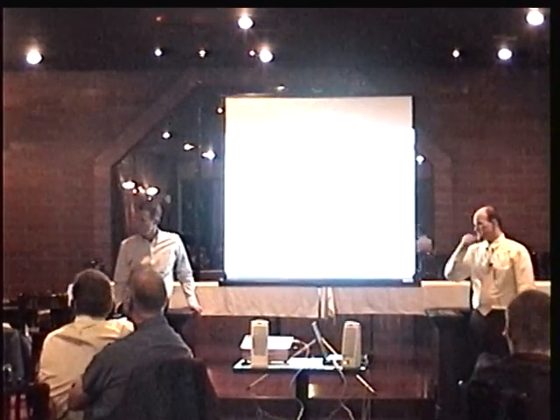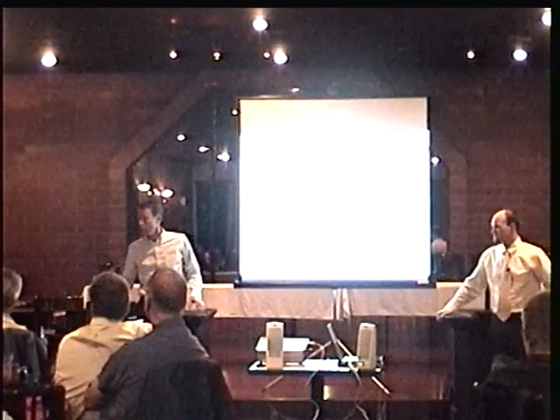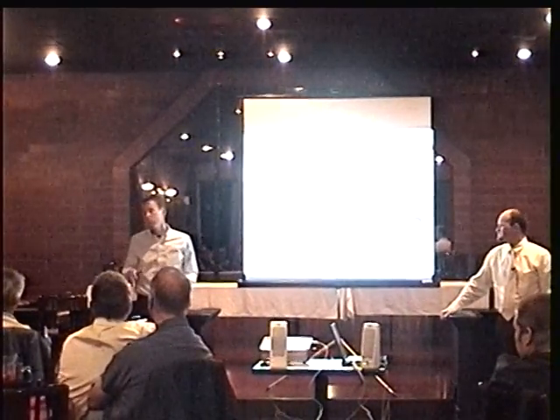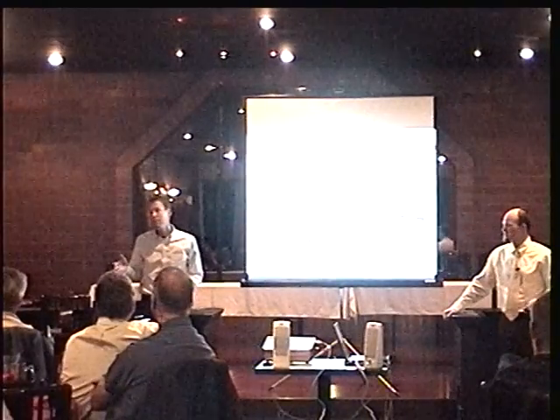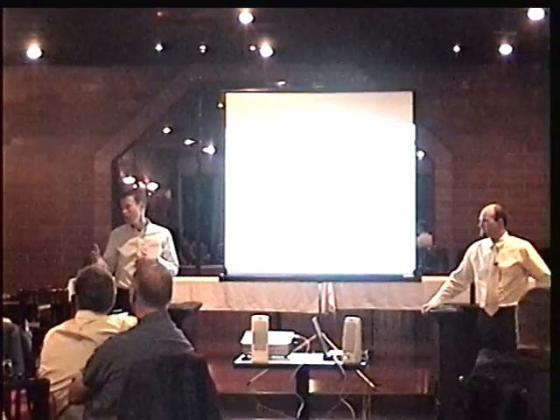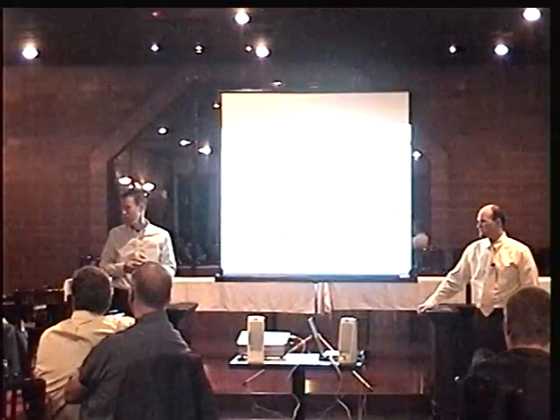Did you measure the events? Yes. Every time? Yeah. How did you measure that? What do you mean, measure events? You can have a bunch of cycles going where you won't have an event, so the crack's not going. But then you'll have an event when the crack starts growing. Well, we followed the E647 standard as far as measuring how often to take measurements. It gives some guidelines, and sometimes it would grow faster, so instead of at 20,000 cycles, you would want to make sure that we get every 50 thou crack growth increments.